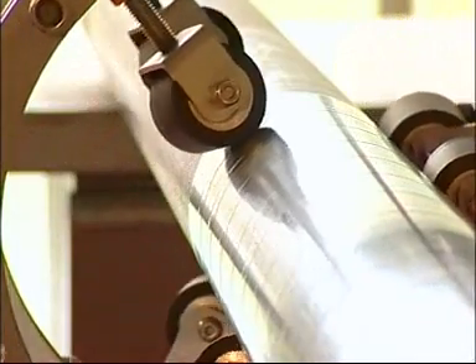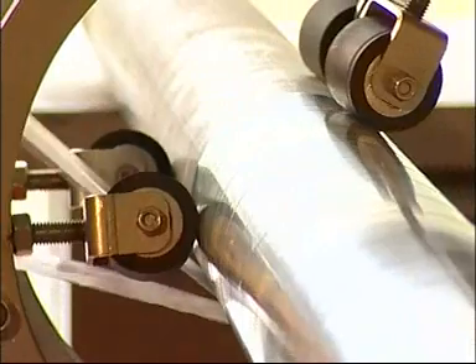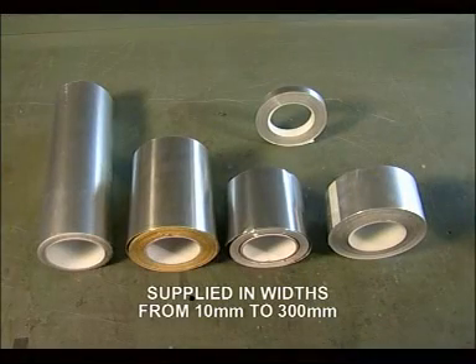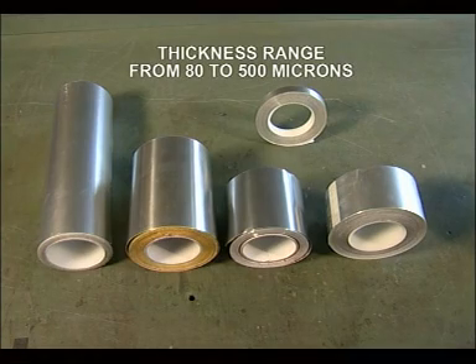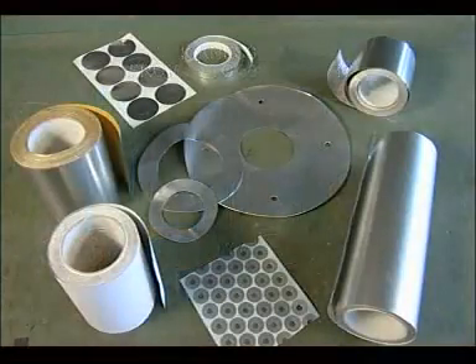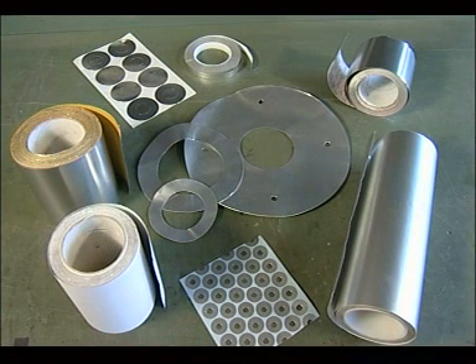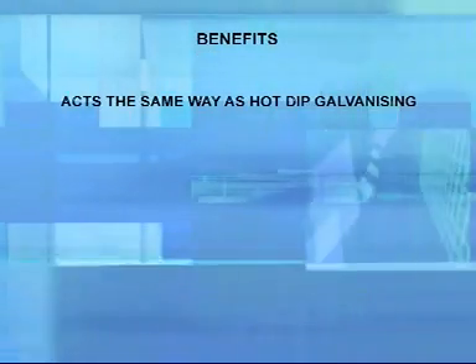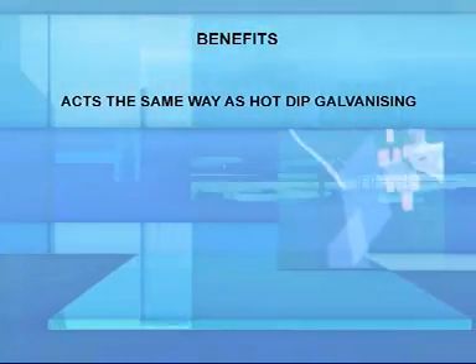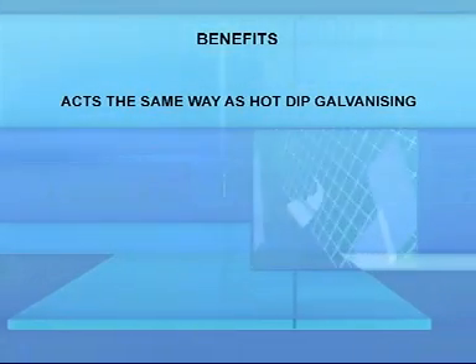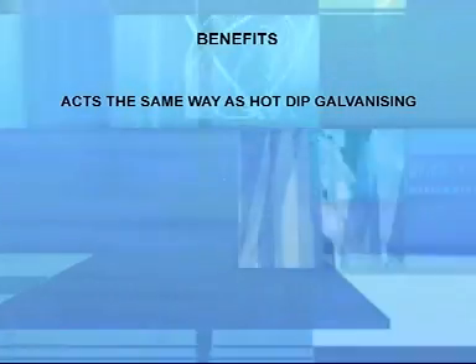Conclusions. Zinc tape is easy to apply and versatile, with tape reels ranging from 10 mm width tape to 300 mm width, and in thicknesses of between 80 and 500 microns. It can also be supplied as washers and gaskets to whatever shapes and sizes the customer requires. Benefits. Acts in the same way as hot dip galvanizing. Eliminates the costly effects of corrosion even if coatings sustain some damage.